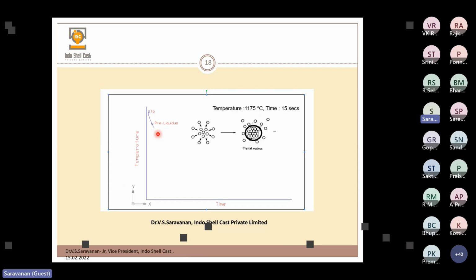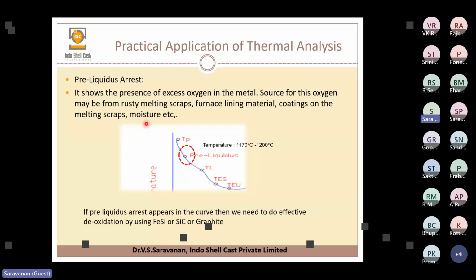So that is called here. This is not a permanent one. This particular pre-liquidus arrest point. So this is actually called the pre-liquidus arrest. Here what happens is, once the nuclei are formed, they dissolve again at this particular point. So what it shows is that this pre-liquidus arrest point sometimes shows excess oxygen, and the source of oxygen